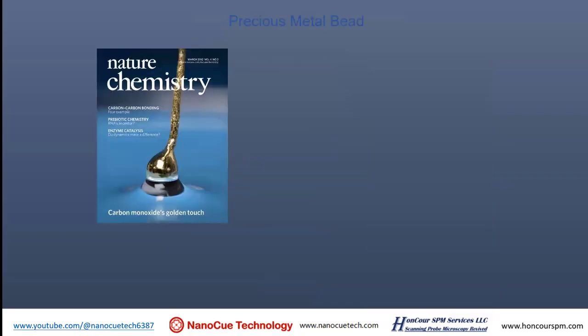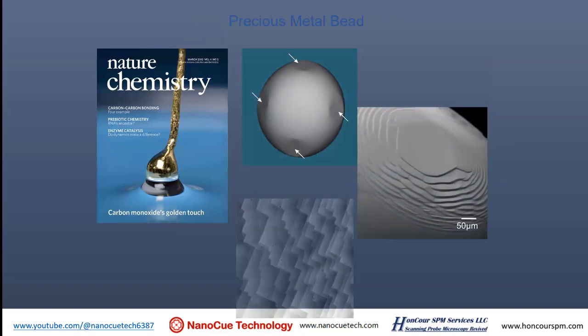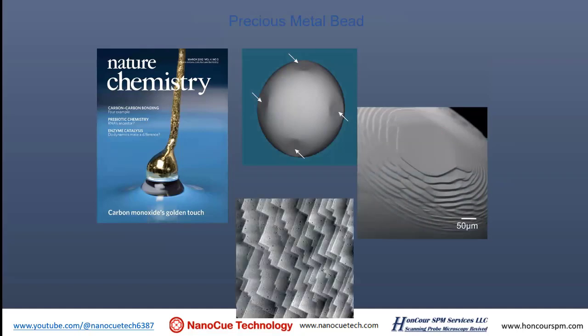There's another way I've been promoting, trying to get people to use it, which is precious metal beads. So here's the one on the left. It's a magnified view of a piece of gold wire, and then you use your hydrogen flame to burn it, heat it at high temperature, and at high temperature, the gold will melt. And then as you melt, it shrinks to a bead, and then you let it cool down. The bead is as small as 2 millimeter, as big as 3.5 millimeter.